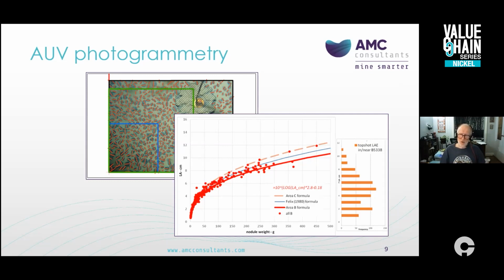The benefits of photos over physical sampling were quickly recognized and include, for example, that they're much quicker and cheaper to collect than with a conventional sampler, and a larger sample area can be measured than with a conventional small sampler. A key limitation of photo-based abundance estimation is that in some areas, light sediment cover is sufficient to mask many of the nodules, which prevents an accurate estimate. Nonetheless, where this is not a problem, LAE is a valuable low-cost supplement to box core data. The method will probably become the preferred method for short-term operations planning.